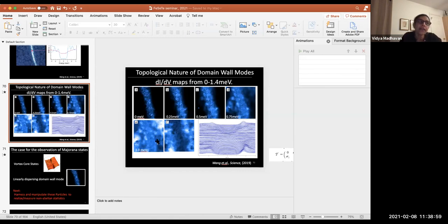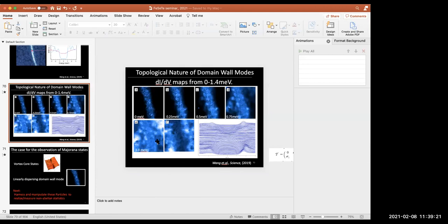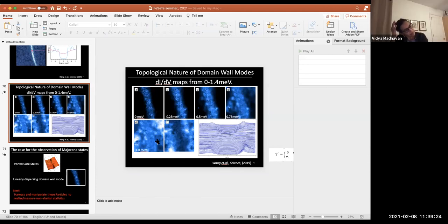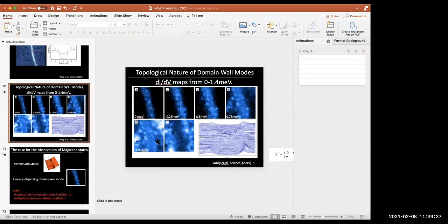Okay. I know that usually if you have an odd frequency superconductor, you'll see a gap, and then it'll be sort of a V-shaped gap, right? And then you're saying you may not have the resolution, you're smearing it out. Typically, you will have some in-gap states, and the STM data that I've seen so far hasn't been particularly convincing. They've been mainly on sputtered multilayers, I think. So there's a lot of spatial inhomogeneity, regions where you have what look like subgaps, regions where you have zero bias peaks as well.